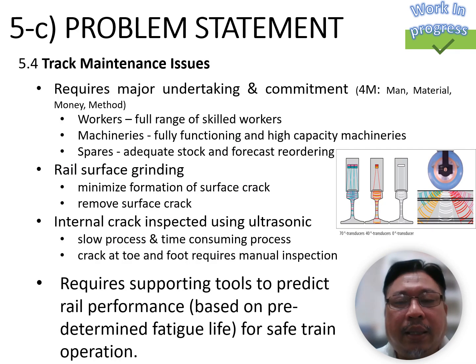The fourth problem regarding reuse of the steel rail material: the maintenance of the track itself requires a major undertaking. It requires full scale machinery, workers, and spares in order to make sure the line is always in operation and operable. There is also a requirement to do regular rail grinding to minimize the formation of surface cracks. Then we also need to do the very important internal crack inspection using an ultrasonic machine. So the use of reclaimed rails needs to be supported by tools or a basis to understand the remaining life of the steel before it can be reused again.